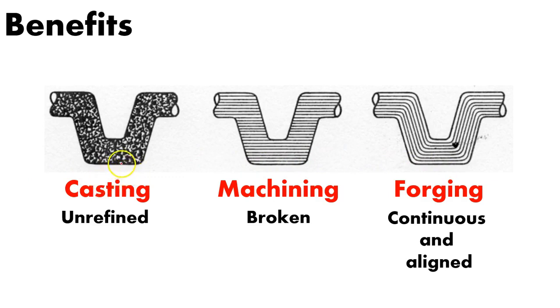If we look at the cast process, you can see that the grains are random and there's no real alignment to them. There's no real order to them. So you can say they're unrefined grains. And this is a much more brittle material. There's not the same alignment. There's much more likely going to be porosity. So there will be a much more likely chance of fatigue failure.